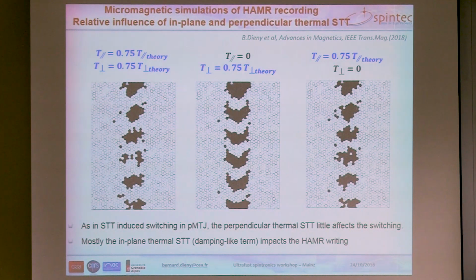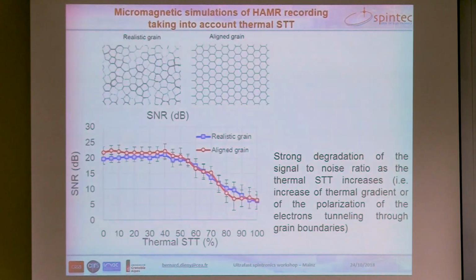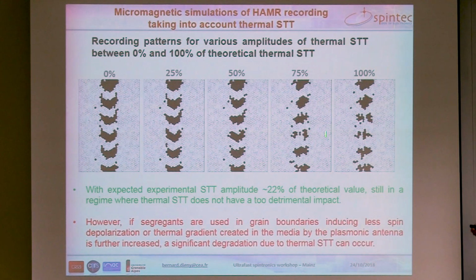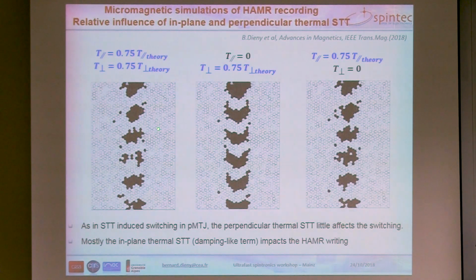Now, something else that we investigated was the relative role of the two components of the spin transfer torque. So here, actually, we are in the same situation as here. So we assume 75% of the full amplitude is present, both for the in-plane and perpendicular component of the torque, and we see that the bits are really badly written.